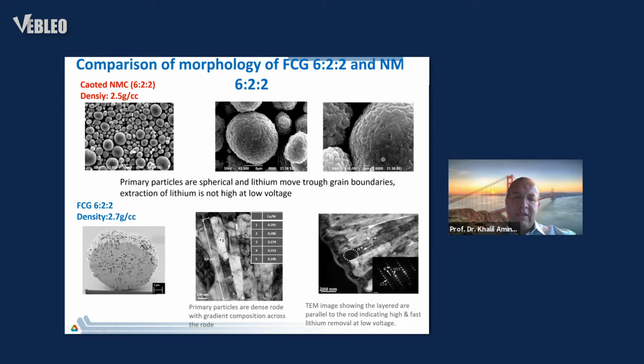We also looked at the concentration gradient within the primary particle. They also change, as you can see from the cobalt nickel ratio changing. Now, the most important observation is that when we did a TEM, we noticed that the layer structure of the material is parallel to the rod, which means lithium can move very fast without going through the grain boundaries. And that can allow us to pull most of the lithium at a defined voltage. What I mean is, for example, if you take these two materials, charge them at the same voltage, let's say 4.3 volt, you would draw more capacity out of the material because of the ease of moving lithium out because of this unique configuration. And we were right.